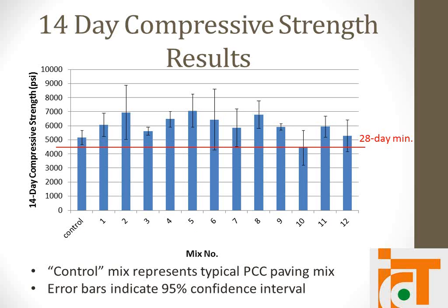We had a control mix that was just a typical plain Portland cement paving mix, to see how RCC compared with it. All of the RCC average values except one were greater than the control, but mixes 4, 5, 7, and 8 were statistically greater than the control, while all of them met or just barely met IDOT's minimum 28-day strength of 4,500 psi. And these were tested at 14 days, so they're far exceeding the minimum strength requirements.